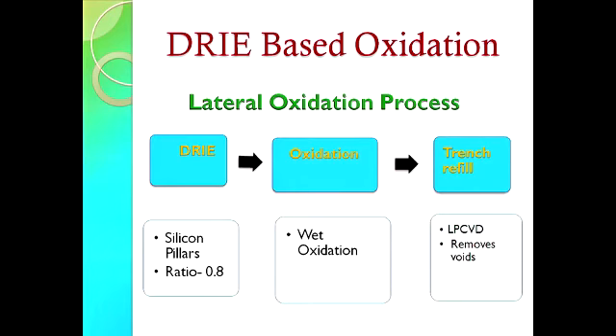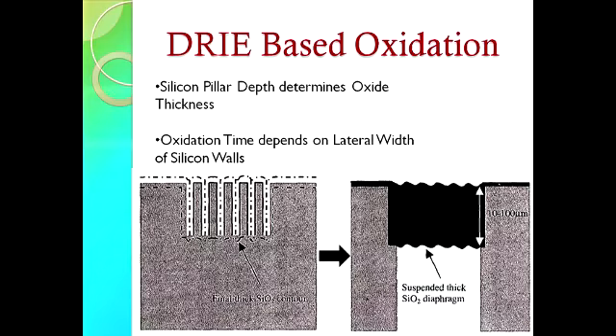This process is followed by wet oxidation at 1100 degrees Celsius, and this process is not the vertical oxidation, but then only the silicon pillars are oxidized horizontally. And then it is followed by trench refill, which is done by LPCVD technique, and this is mainly done in order to avoid voids, because in the wet oxidation process there are voids formed, and so LPCVD technique removes it. So this is how the process looks.